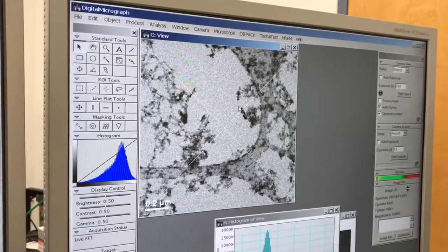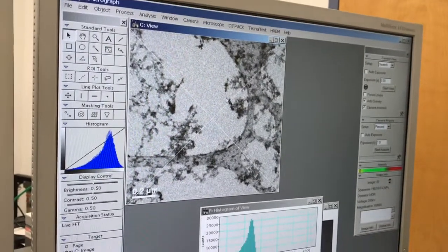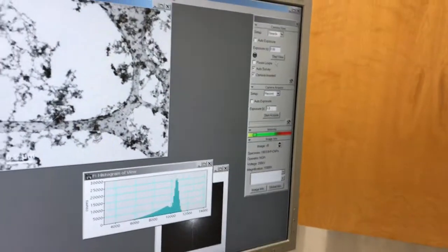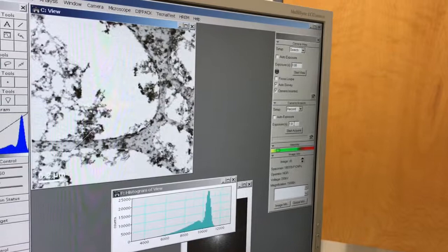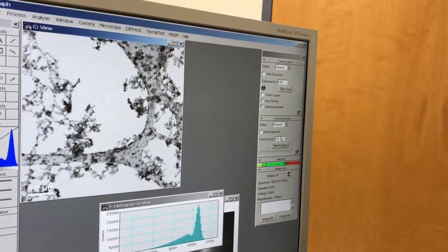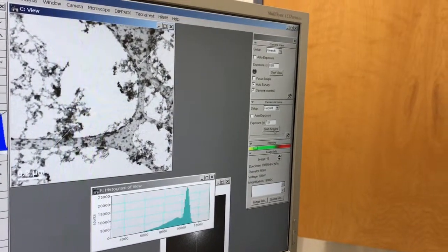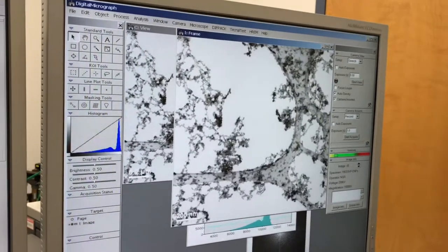So if we go back to 0.08, I'll use a multiplier of about 10. I've got 1 here, and that usually works well. That's a little less than 16, but you'll see here it does produce a good image anyway. And there's the final image.